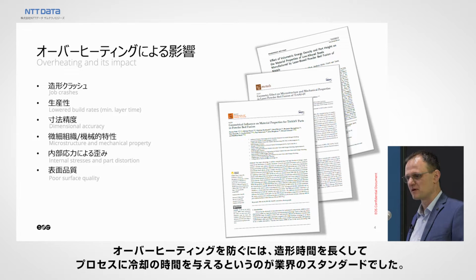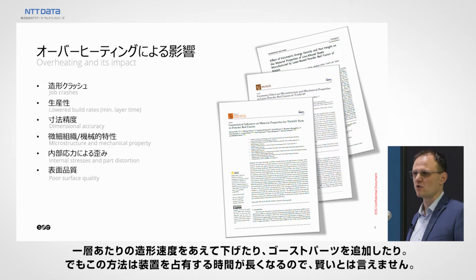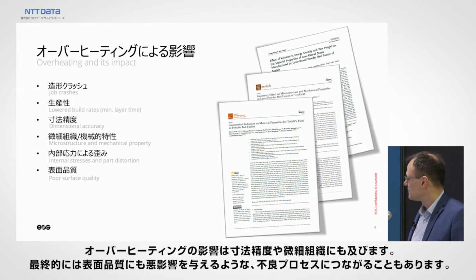What the industry standard so far always was with regards to preventing overheating was to lower the build rates, to take speed out of the process, to give the process time to cool down by adding minimum layer time or ghost parts where no component was really built, but the machine was just sitting there idle. It's also not ideal. You're wasting or losing money. You can run into dimensional accuracy, microstructure and microscopic property problems, but you can also have internal stress deviations in your process, or it can ultimately lead to poor surface quality.